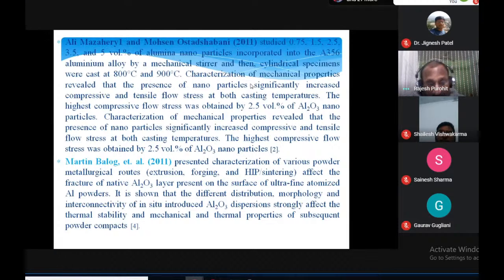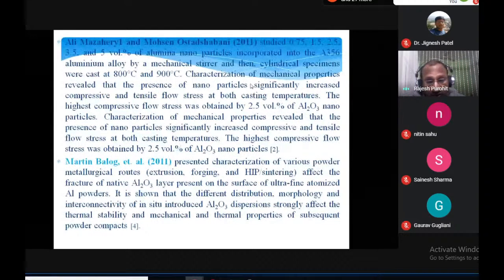Then again another author, Martin Balog et al. presented characterization of the various powder metallurgical routes: extrusion, forging, and HIP. HIP is basically hot isostatic pressing, and then sintering. Effect of the fracture of the native aluminum oxide layer present on the surface of the ultrafine atomized aluminum powders was studied. It is shown that the different distribution, morphology, and interconnectivity of the in situ introduced aluminum oxide dispersion strongly affect the thermal stability and mechanical and thermal property of the subsequent powder compacts. So here basically in situ process was used to fabricate the powder. Basically the aluminum oxide is formed inside the metal by in situ process.